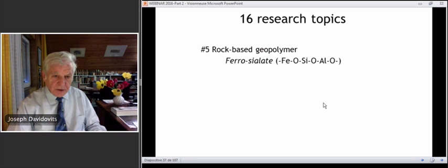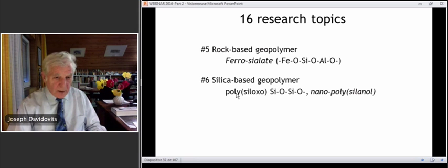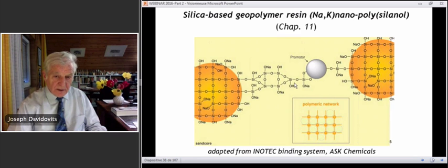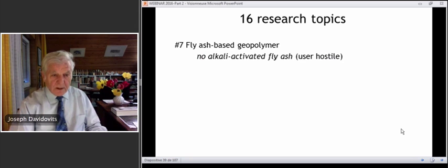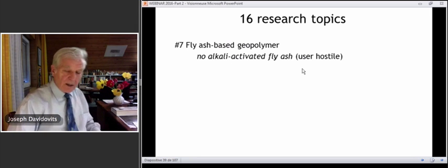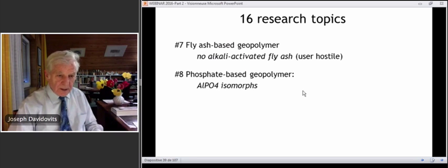This is a very important issue. We have silica-based geopolymer. These are the polysiloxo, polysilanol chains that have these structures. We have polysilanols in between silica clusters, and this is used for foundry applications. Fly ash-based geopolymer, we do not propagate the use of alkali activated fly ash, user hostile, made at high temperature.